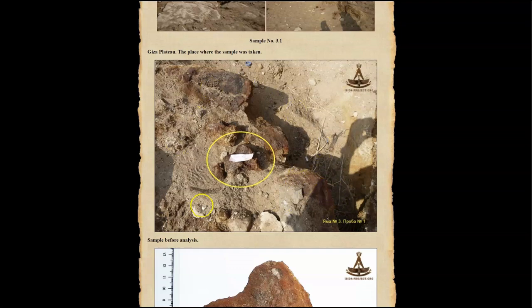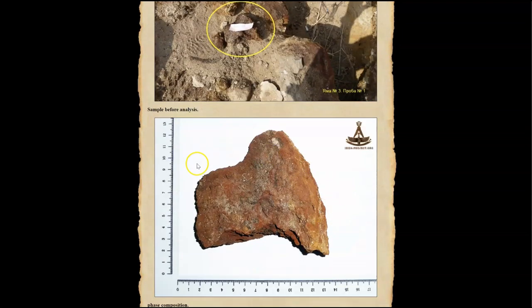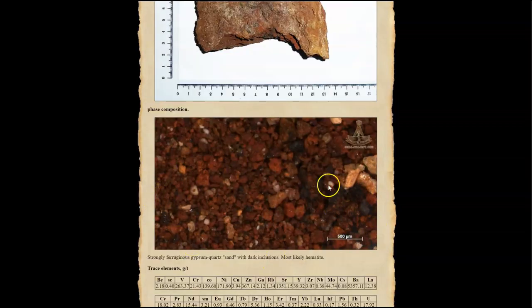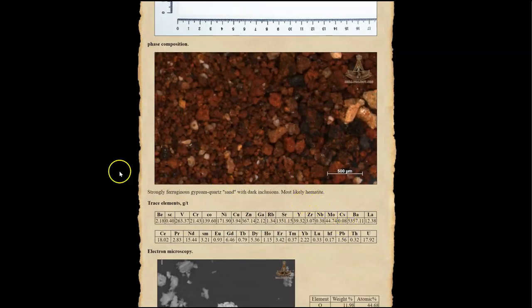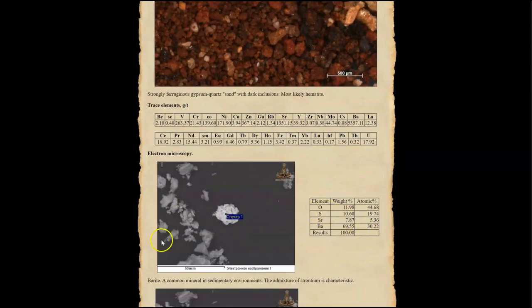And here is the first sample location, an image of the material, and a close-up, processed and microscope image described as a strongly ferruginous gypsum quartz sand with dark inclusions, most likely hematite. And there is no macro analysis on this one, but it is mostly iron oxide just like all the rest, and this one has a notable amount of barium. As you can see here with this particle of barite, 69% barium.